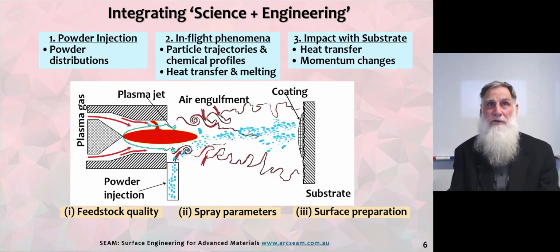So thermal spray processing integrates science and engineering. So we have powder injection, in-flight phenomena, and impact with the substrate. We have a diagram of a plasma torch, and in the process of thermal spraying, there will be air engulfment. The particles which go into the plasma effluent by particle injection may oxidize, and then at some point, usually about 6 inches or 15 centimeters from entry, these individual particles will splat and form saucer-shaped deposits against the roughened substrate.